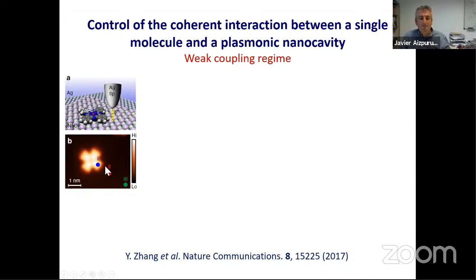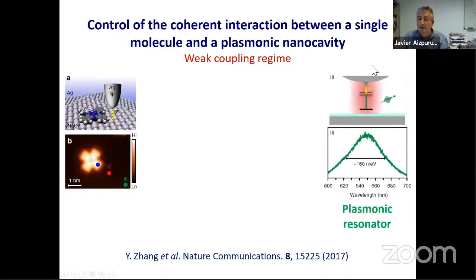So we can put the plasmonic cavity by locating the tip in position one on top of the molecule, or very far, position three, or in between. If we put it very far, it will not interact at all, and you will get just a spectroscopy, the emission of the plasmonic mode, the resonator mode. And this is what I show you here, right? We put the tip very far from the molecule, you excite, instead of light, with an inelastic current of electrons, and then you record the light emitted, and this light shows this broad plasmonic resonance. This is the plasmonic cavity or plasmonic junction resonance, okay?